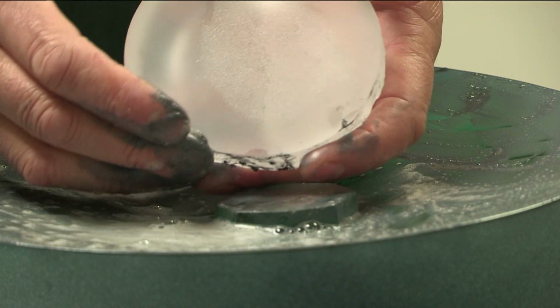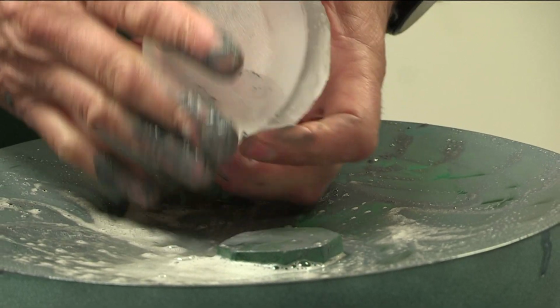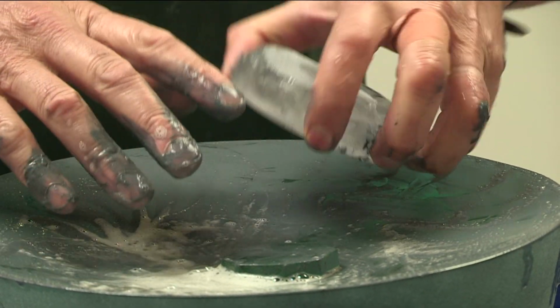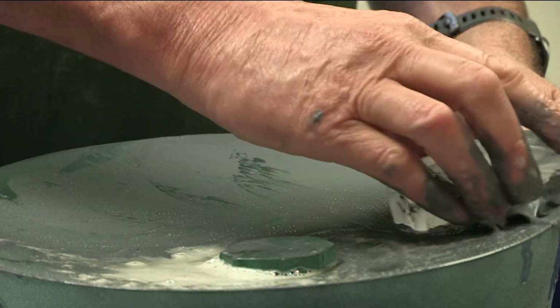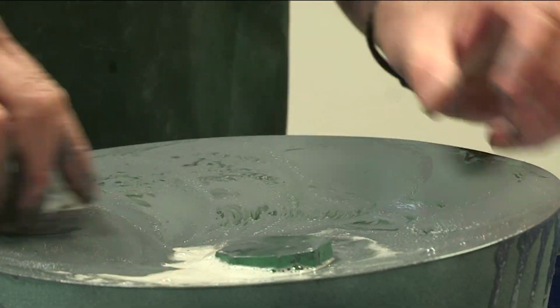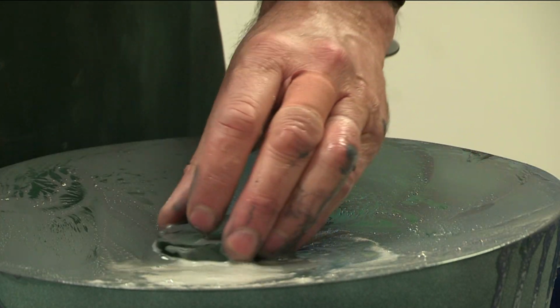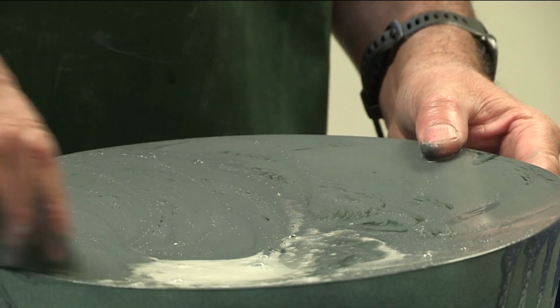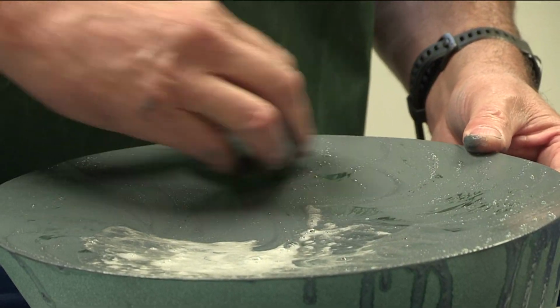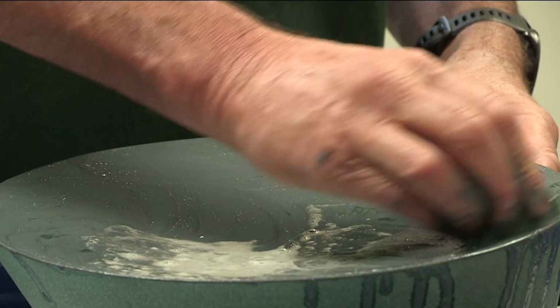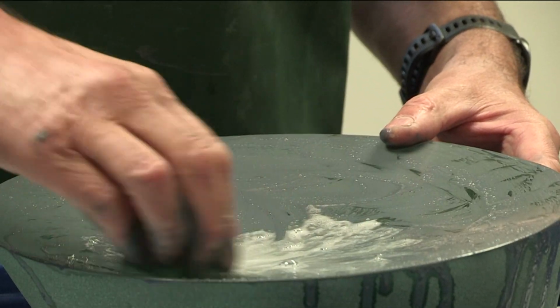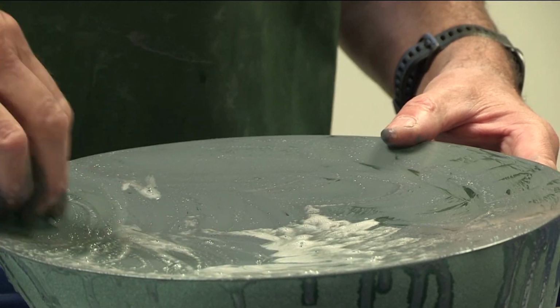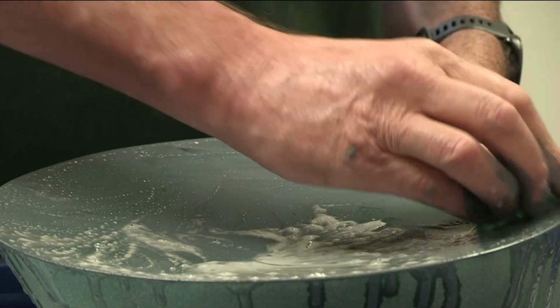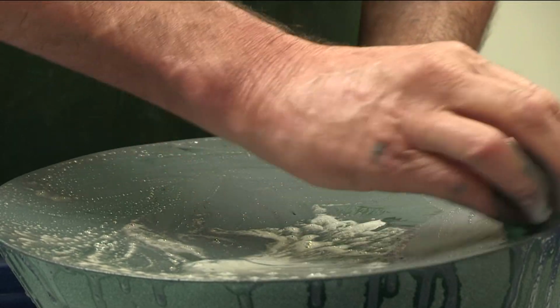When I started grinding with the 80 grit and I was using this large piece of glass, it wasn't even ground to the same shape as this, but it just evened itself out very quickly as I'm grinding it around the surface here. Another addition, I'll go back to using my small bit of glass, but another addition to the grit, other than just a little bit of water, is a little bit of detergent. You can see there's sudsing in there. It just makes the grit less sticky, and there's less opportunity for the glass to cause a suction and get pulled into the surface.